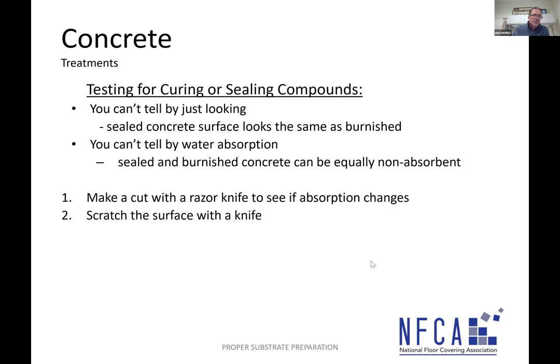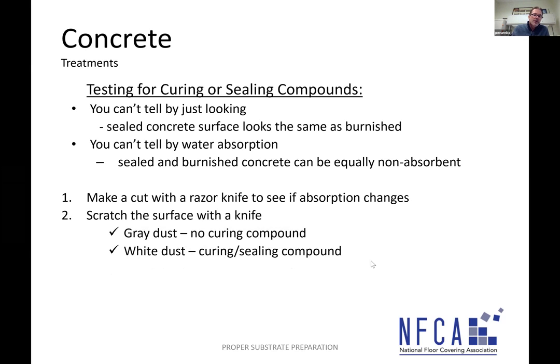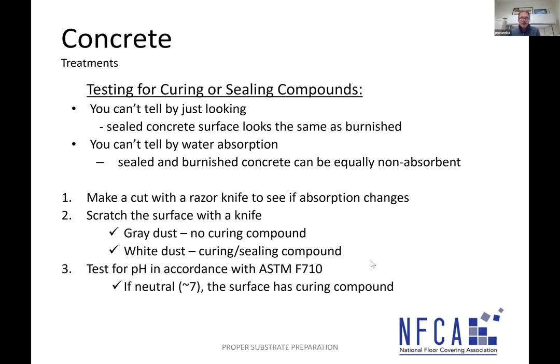We can also scratch the surface with a knife. Okay, if we see gray dust, then we're scratching the concrete. If you take any type of clear film and you scratch it with a knife and flake some of it off, it typically appears white. So if you're flaking little bits of white off there, there's a good chance that that's a curing compound or some sort of sealer that's on the surface. And lastly, you can test for pH. Do a pH test, okay? If there's a sealer on the surface of that concrete, you're not going to get a pH reading of acidic or alkaline. It's going to be more neutral, okay? If it's concrete and you do a pH test, you're going to get a pH of 9 or 10, something like that, because that's what concrete tests at. So just some guidelines there for testing for curing and sealing compounds.